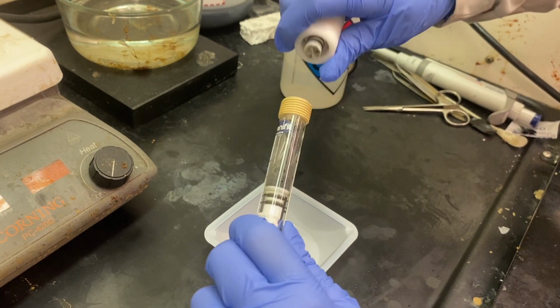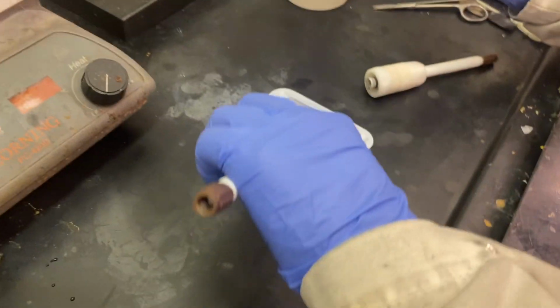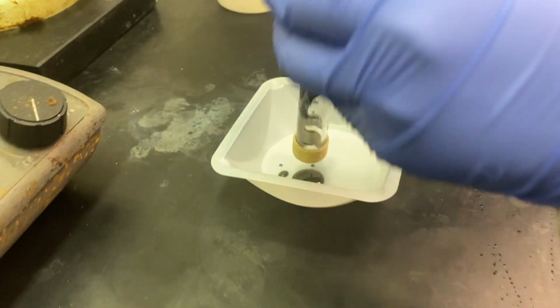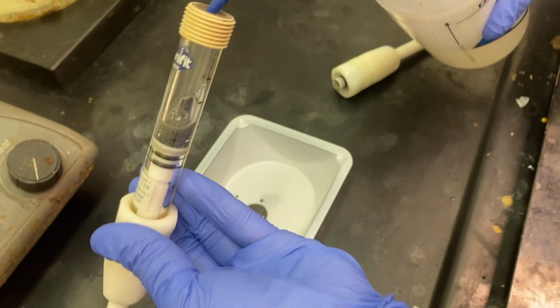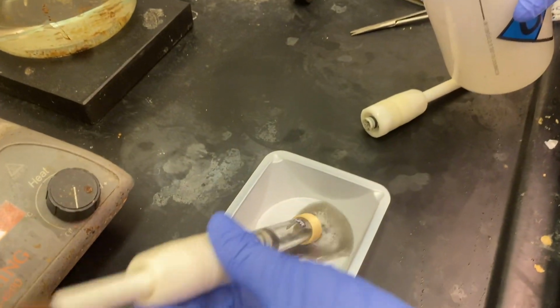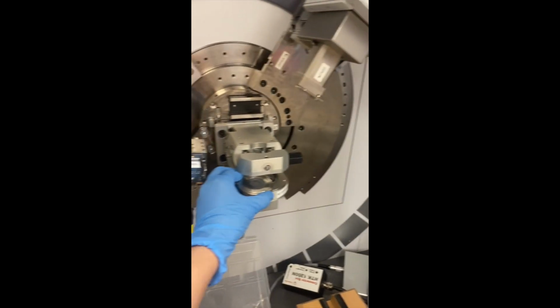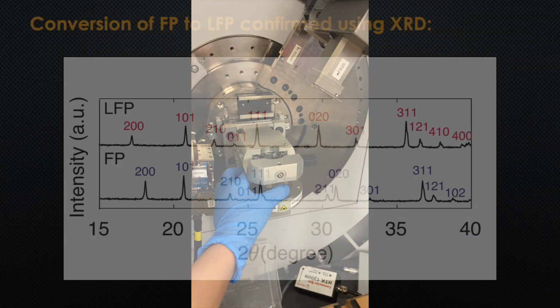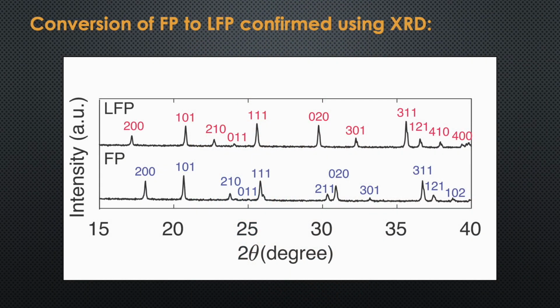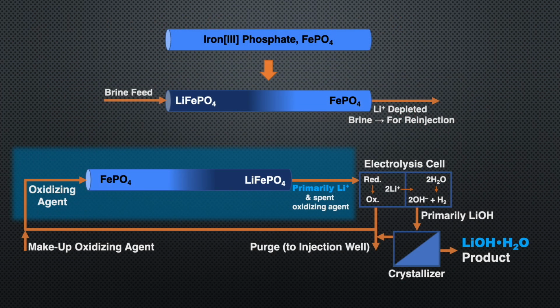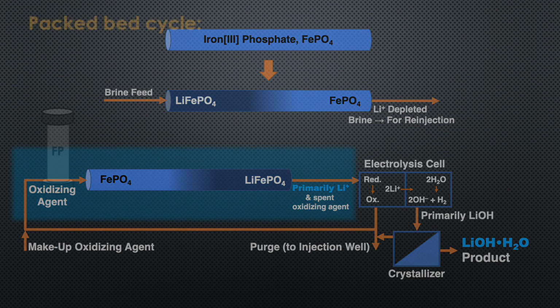For analysis and verification, the lithium iron phosphate particles can be removed from the column after intercalation, and X-ray diffraction, or XRD, can be used to verify the conversion of iron phosphate to lithium iron phosphate, as can be seen in these XRD data, where the 200 peak is a representative indicator of conversion between iron phosphate, or FP, and lithium iron phosphate, or LFP. Following the intercalation process, lithium can be released from the packed bed using an oxidizing agent. Let's take a look at the overall packed bed cycle.